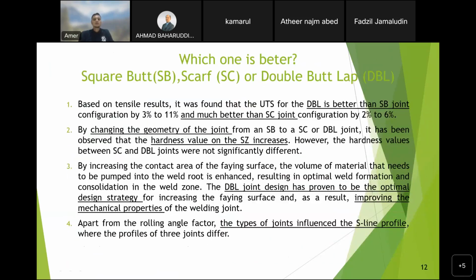So which of the joints is better? Square butt, scarf, or double butt? Based on the tensile result, it was found that the UTS for the double butt lap joint is better than the square butt joint configuration by 3 to 11% and much better than the scarf joint configuration by 2 to 6%.